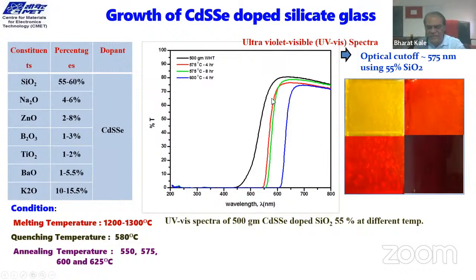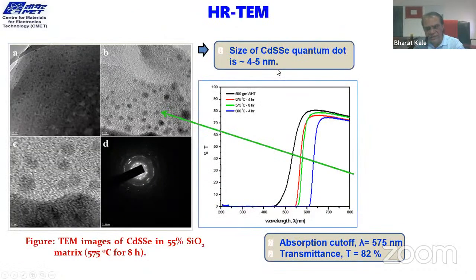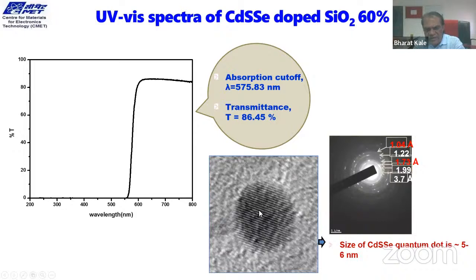So the band gap is changed with the size of the CdSSe, and here in the CdSSe of 4.5 nanometer, you can see very isolated particles. You can see quantum dots of 4 to 5 nanometers, and you see the ED pattern is much crystalline. So it shows good crystallinity. This is again an isolated quantum dot of 5 nanometer. They are very sharp. It shows the sharp transmission spectra. It indicates that the size of the quantum dots is quite uniform. This again the UV clearly showed.